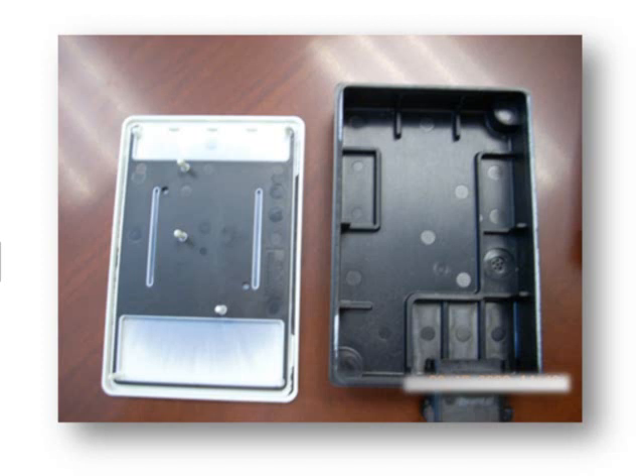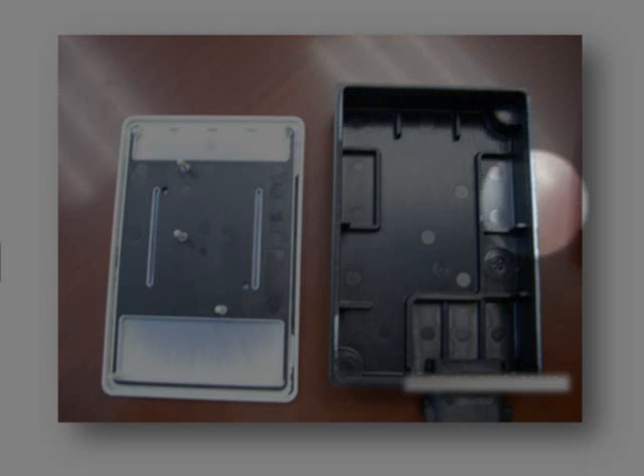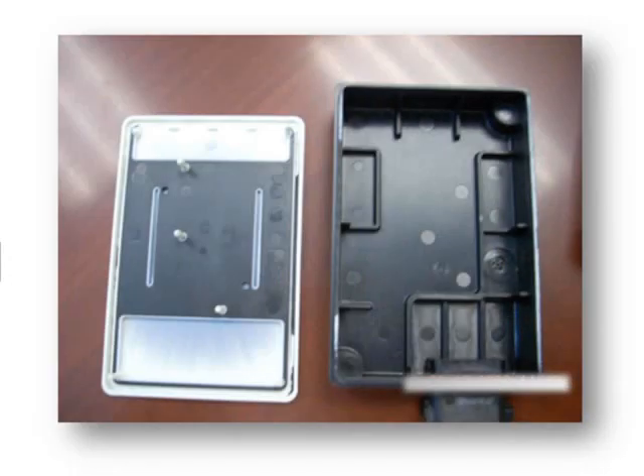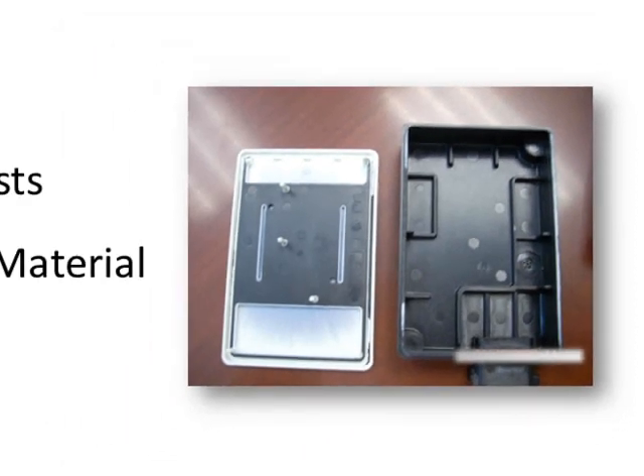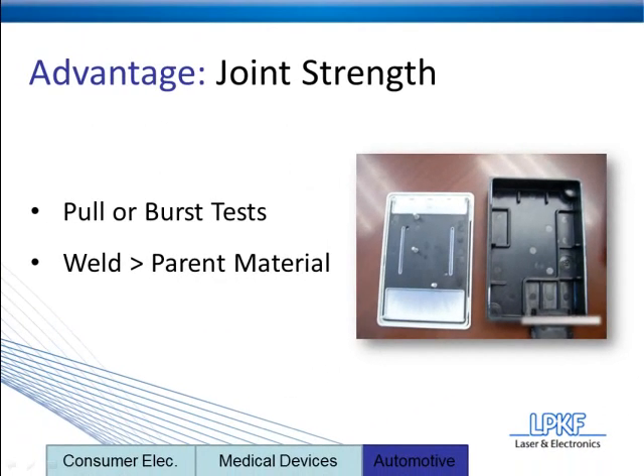Now, in this application, you can see that this white part is a lid, and this originally sat on top of this housing, and the joint would be all along the edges. Now, what we're looking for here is material transfer. So you can see black transfer here and some in the corner, and then on the housing you can see white transfer here, here, and then all along this edge. Now, what that tells us is that as these two pieces were broken apart, the breakage occurred not in the weld, but in the parent material, and some of that material was left on each of the two pieces of plastic.